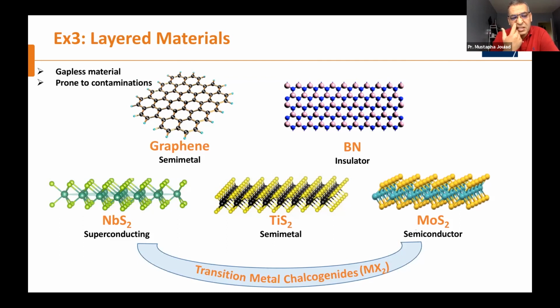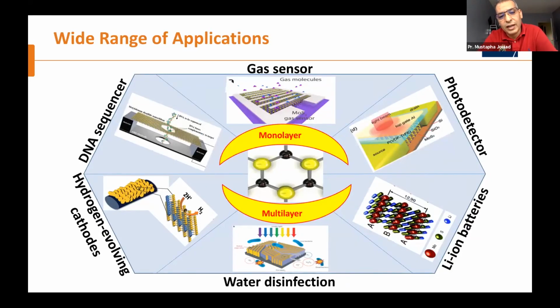Why? Because graphene is gapless, so we cannot tune the band gap. We cannot use the properties of a semiconductor, and it is also prone to contamination. For example, for sensing, graphene is not reproducible as it is sensitive to the environment. It's not the case for MoS2, which has a band gap and is also relatively more stable compared to sensitive materials. So if it is stable, we can produce it. Before getting to that, I will quickly show you the applications of MoS2. It depends on its form. If it's monolayer or multi-layer, it can be used as a gas sensor and so on. I'll let you see all the possibilities. It can even be used in DNA sequencing, hydrogen evolving cathodes, lithium-ion batteries, photodetectors and so on.